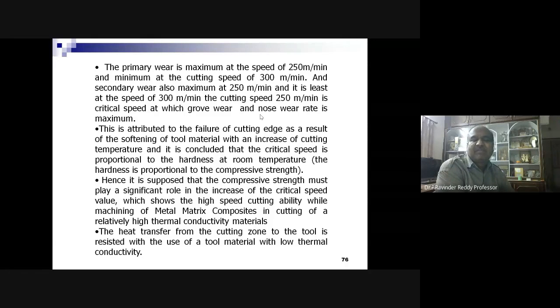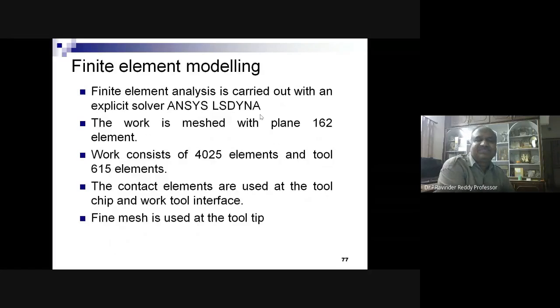while machining of metal matrix composites and cutting of relatively high thermal conductivity materials. The heat transfer from the cutting zone to the tool is resisted with the use of tool material with low thermal conductivity. The same for tool wear, we wanted to model, simulate, and find out the wear rate.